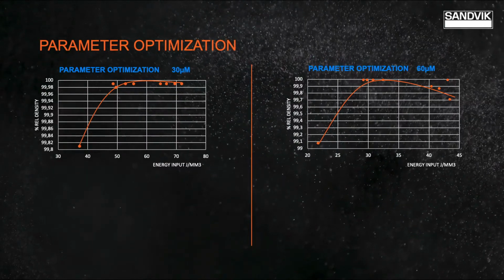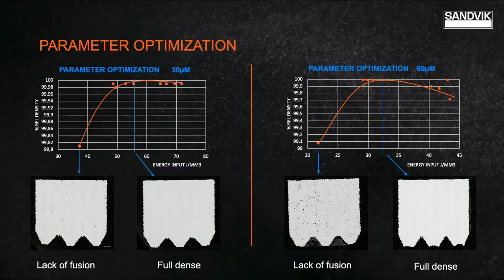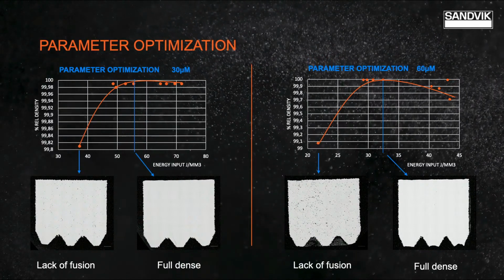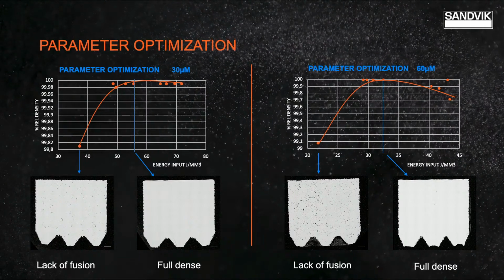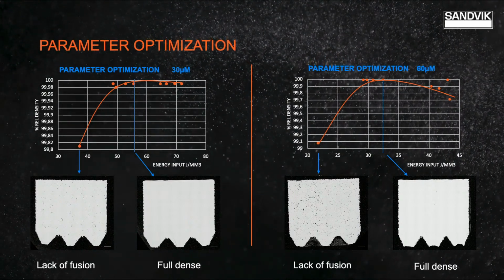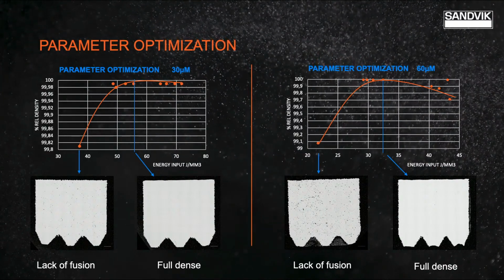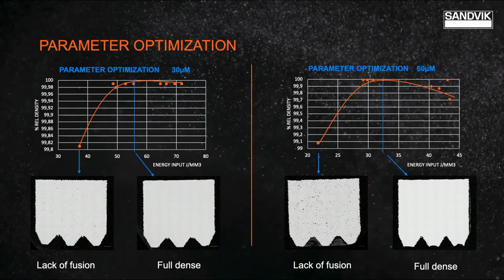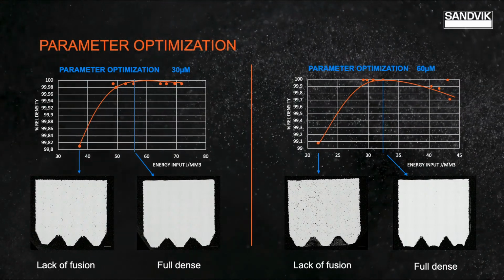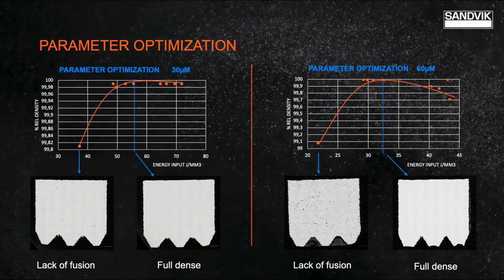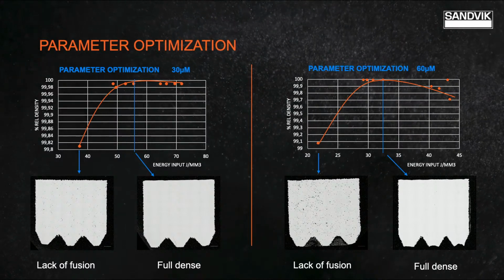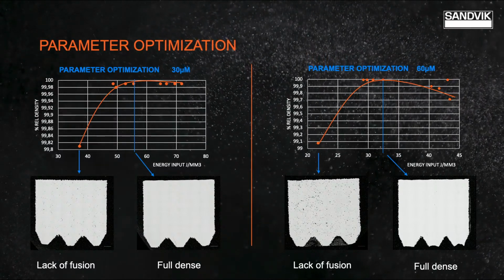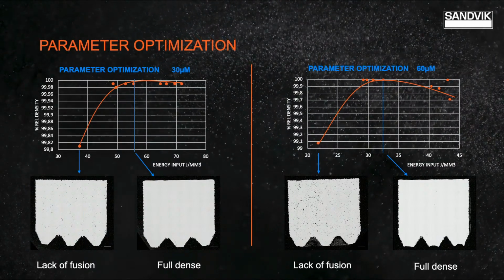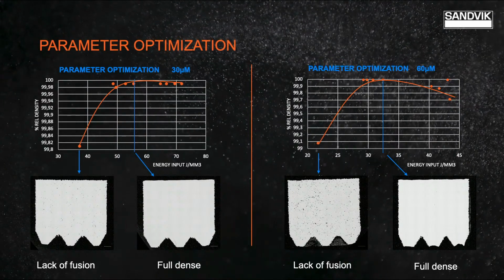Yeah, parameter optimization is an iterative process. We basically vary the energy density of the laser. That means the energy input into the powder during the print process, and print then test cubes in a design of experiment arrangement. Then we cut and polish the cubes and analyze them under a microscope to get the relative density and the feedback on the kind of defects. And what you see on the diagram on the left shows a range of different input energies. Where the energy input is too low, you have low relative density, and there you see a lack of fusion. And where the energy input is just right, you get up to full density, and this is what you want to see.